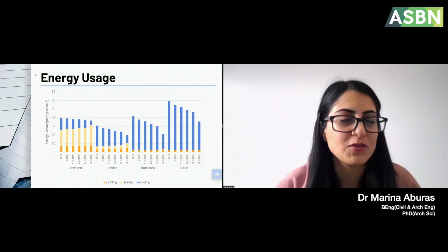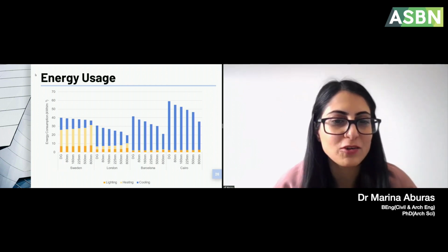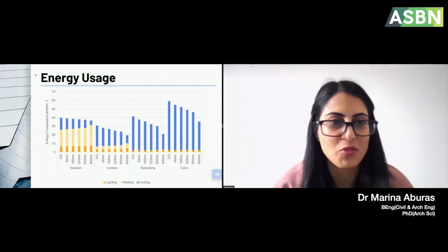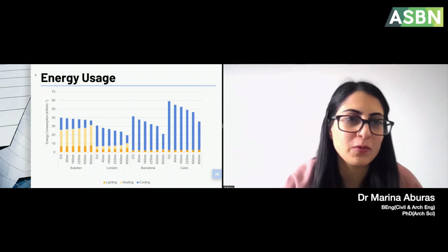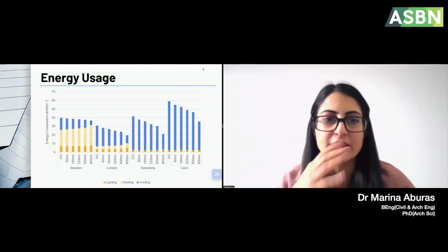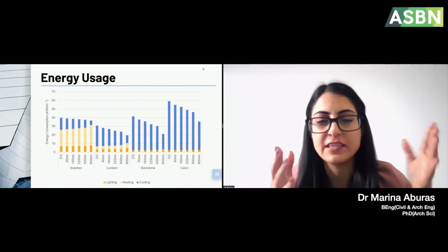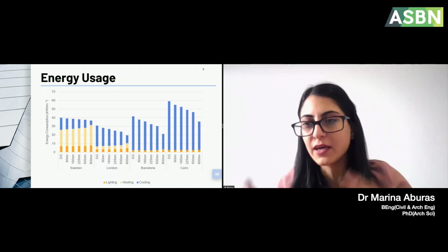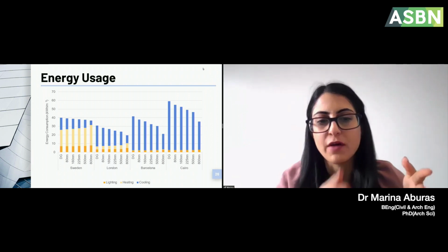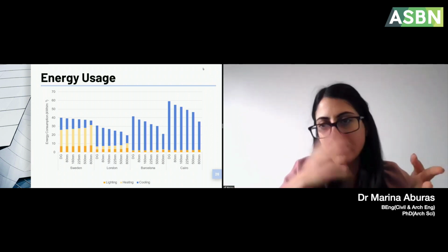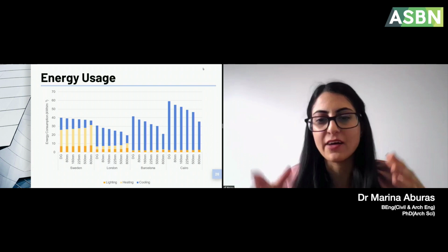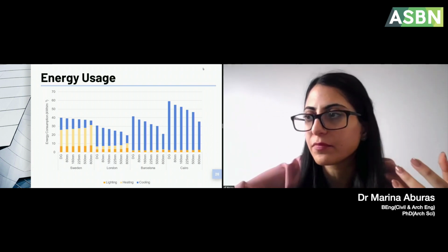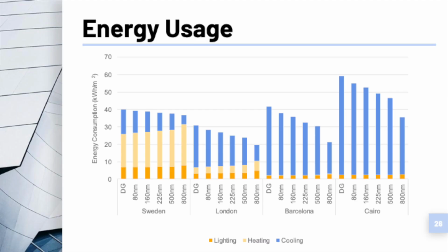And now the fun part, which is really where we wanted to see what happens to the energy usage in a building when you have these smart thermochromic windows. So the results are broken down so that you can see energy consumption on the y-axis for the different climates in Sweden, London, Barcelona, and Cairo. And they're split up so that you have a double glazed comparison and the different thickness coatings, breaking that down into lighting, heating, and cooling. So you can see that the lighting load remains relatively low in all of the climates, but it's really the heating and in particular the cooling that varies most significantly.